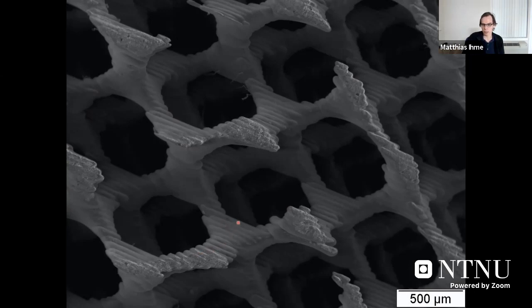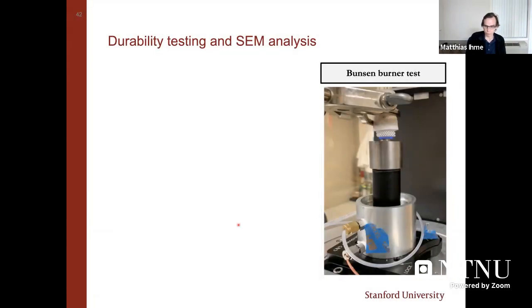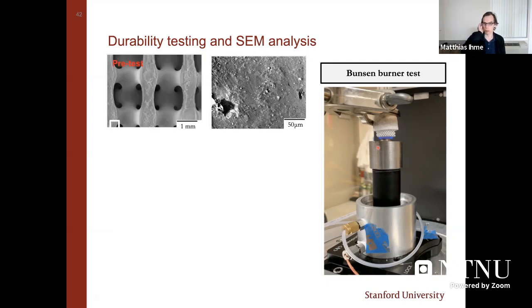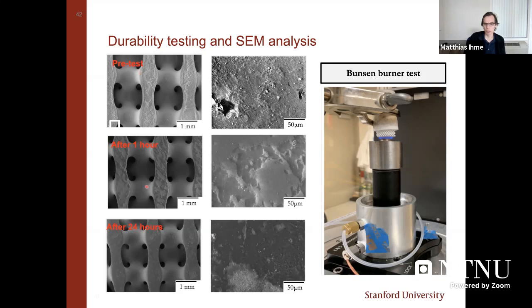It turns out that the layering thickness in how you operate this manufacturing process determines the stability, and with this we can also control the thermal properties. I want to show you some results of this as well. In the next step, we operated this burner that you can see here in this setup, in this high temperature environment, where we essentially exposed this to a combustion product, and performed a cyclic operating test or durability test. I'm showing here SEM images of the structure pre-testing, after 1 hour, and eventually after 24 hours. What we observed is that for this silicon carbide, we didn't see any thermal degradation, which allowed us essentially to demonstrate the viability of this system for high temperature long-term exposure.